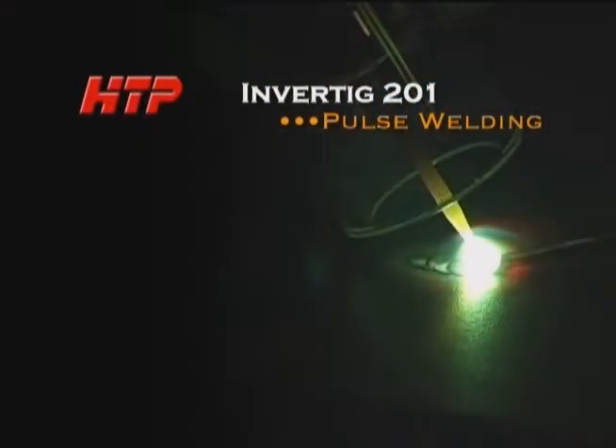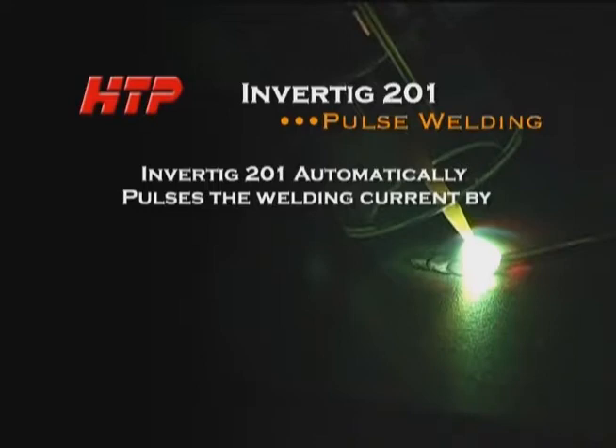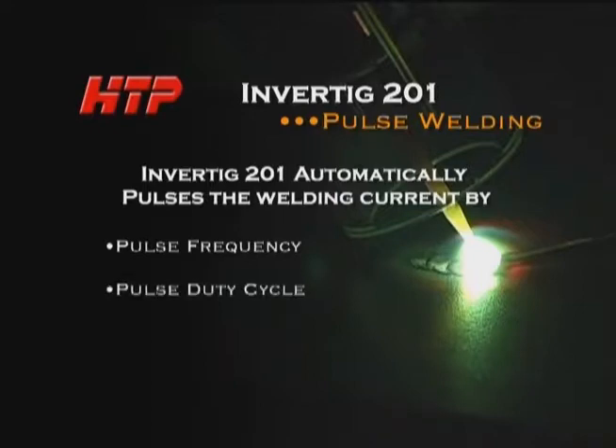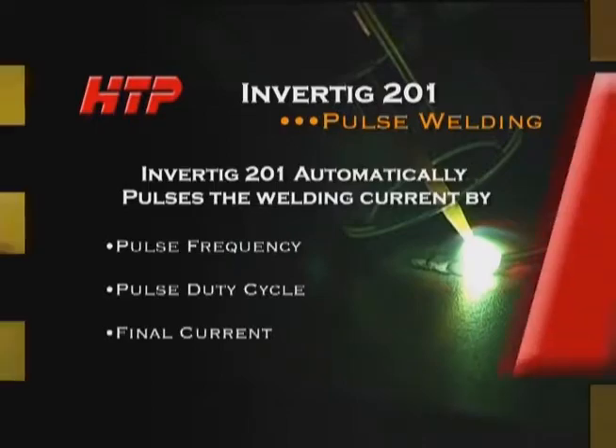Pulse welding is when the InverTIG 201 automatically pulses the welding current. The InverTIG 201 allows you to control the pulse frequency, which is the number of times per second the machine pulses, the pulse duty cycle, or the percentage of the time during the pulse that the machine will be at the higher welding current, and the final current, which is the current the machine pulses down to in a percentage of the peak current or the welding current.